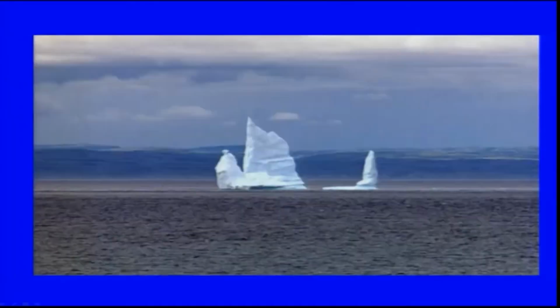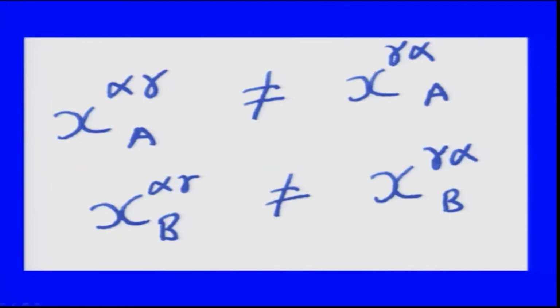Now when this condition is not satisfied, what will happen? Then this equality will not hold. These are actually equalities in composition. So you understand that composition equality is not the condition for stability. The chemical potential must be equal across the interface.